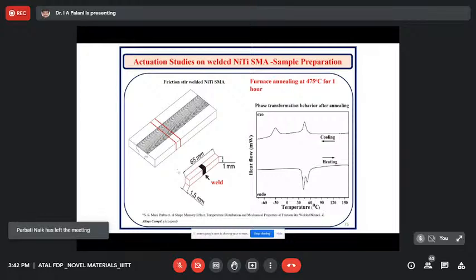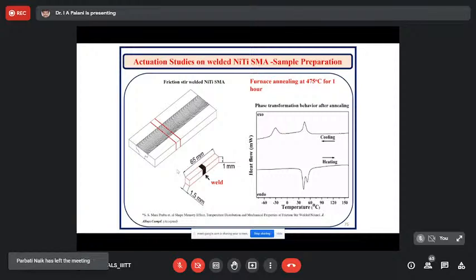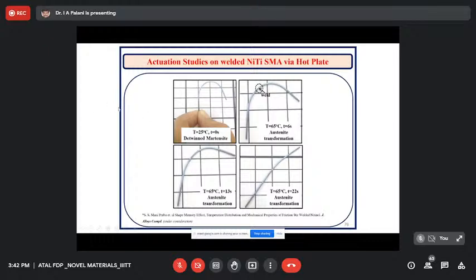We did some sample preparation. We went for a certain amount of furnace annealing on it, and with respect to furnace annealing we were trying to see the capability of it. We had two materials, and we used a friction pin over it and welded it, and we have studied the phase transformation coming out of it. Okay, so this is the overall picture of a friction stir welded shape memory alloy structure.